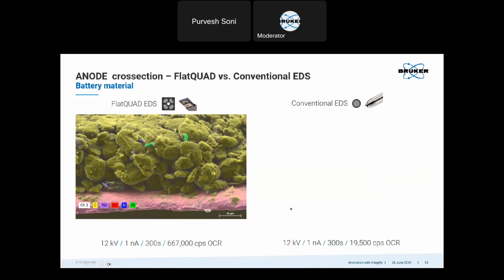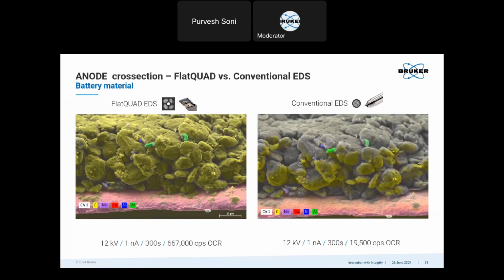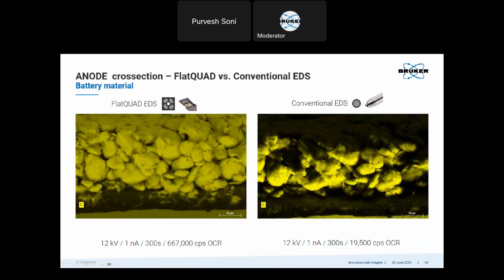And this is an anode cross section measured with the FlatQuAD and with the conventional detector at 12 kV and 1 nanoampere. You can see the enormous output count rate that I get for this material, and with a conventional detector, it's barely 20,000 counts per second. What is interesting to see is that we have very good signal collection, and the data from, let's say, shadowing of the material is all there, but with the conventional detector, there's a lot of data loss.